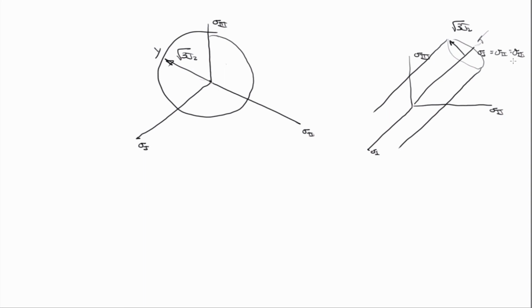And so I think you can probably see where one of the modifications is for rocks. That's what I said is not true about a rock. If I squeeze a rock hydrostatically, eventually I'm going to collapse the pores, and when I let it go, it's not going to pop back. It'll pop back some, but the pore collapse is going to be permanent.